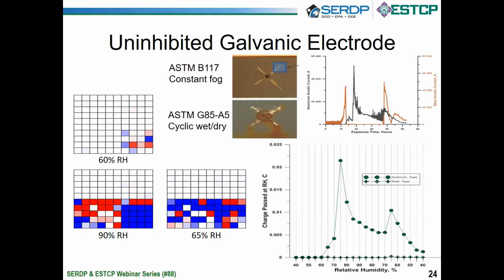And then as you go back through the drying, starting to dry it off, dropping back down through deliquescence, you see that the steel starts corroding again as the aluminum shuts off. The other thing that I'll mention about this is that we can integrate this as a function of time and measure the charge. So the charge is directly related to the amount of corrosion that's happening. And I'll just point out this data from the aluminum because the steel is on a bad scale here. But as you go through these points, you see these spikes in this data here. And basically, this is increased corrosion rate as you go through wetting and drying. So this is under more or less steady state electrolyte conditions.